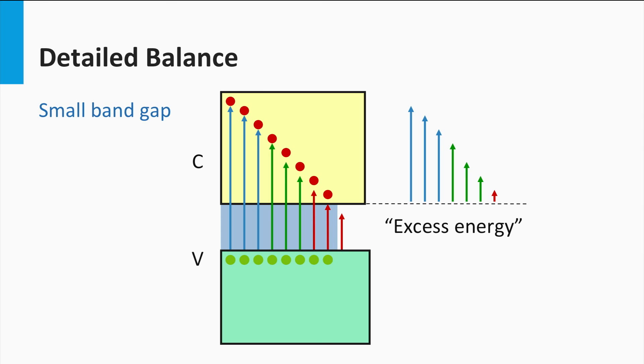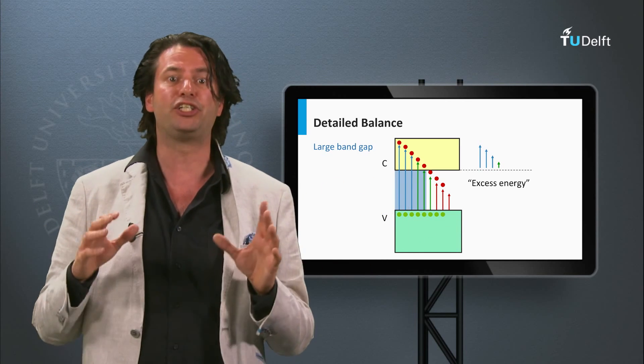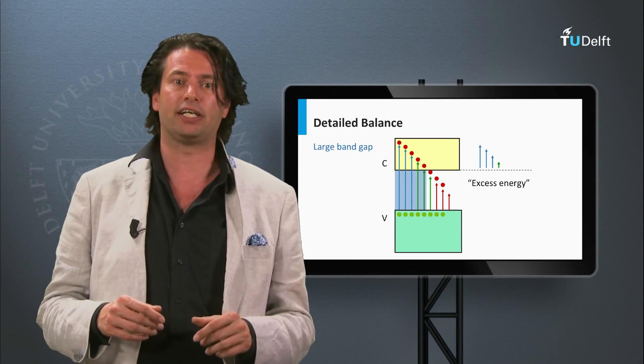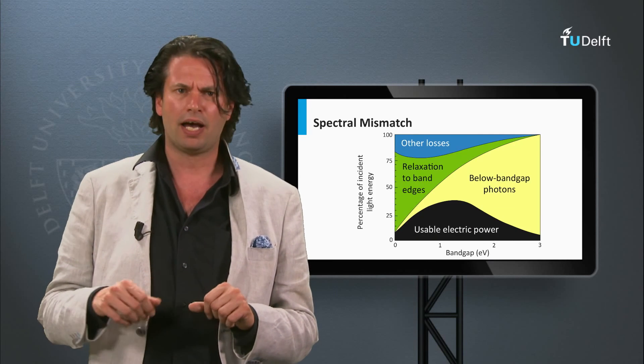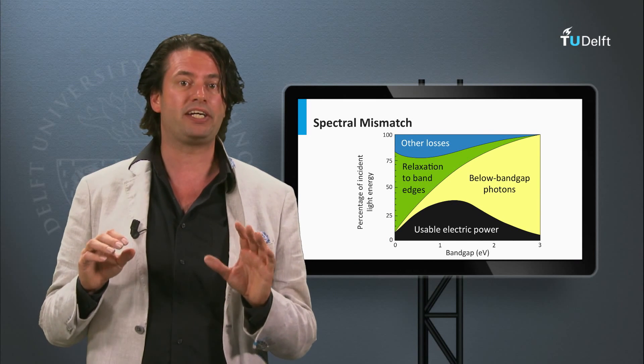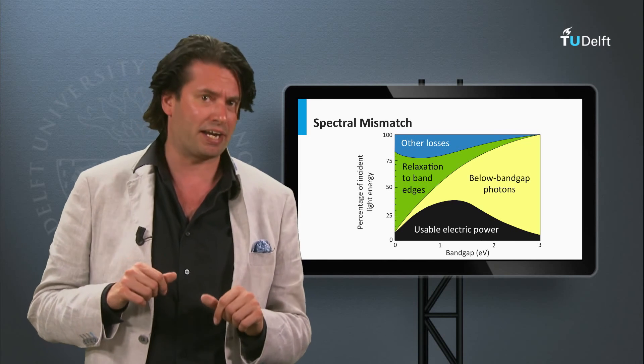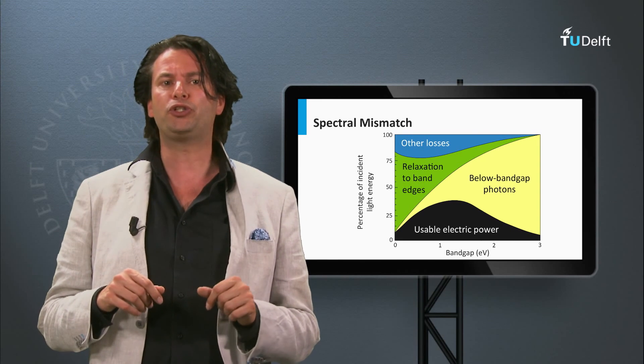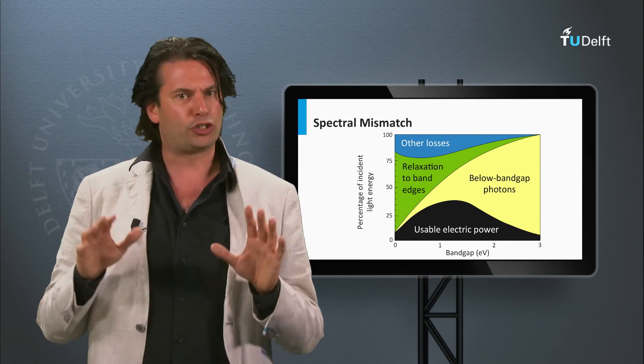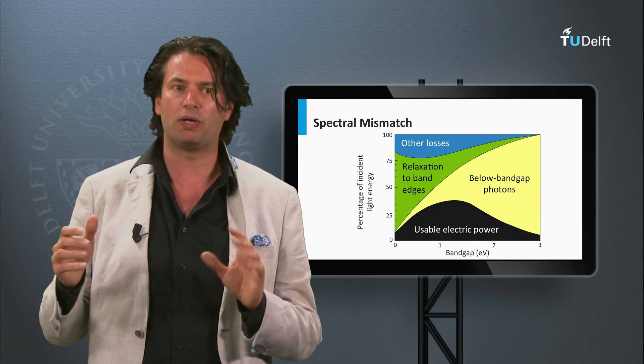Therefore, radiative recombination is enhanced for low band gap materials. For a high band gap material, the energy loss below the band gap is dominant, and the excess energy determines the amount of charge carriers that radiatively recombine. The figure shows the loss mechanisms: black body radiation, relaxation of charge carriers to the band gap edges, and lost energy below the band gap. The Shockley-Queisser limit has an optimum of 33% for band gaps in the range of 1 eV up to 1.5 eV.